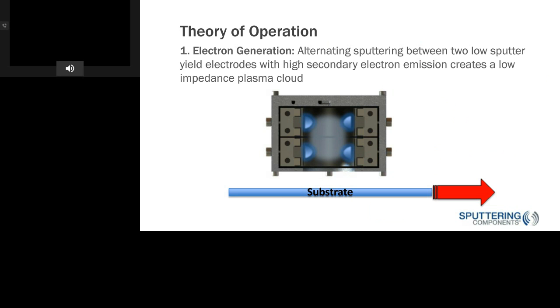So in stage 1 for electron generation, there's alternating sputtering between the 2 low sputter yield electrodes with high secondary electron emission. And that creates the low impedance plasma cloud that you can see, this sort of grey cloud here. And the substrate is below, so the plasma will expand out to hit that substrate. And this can be either a static substrate or a moving substrate.